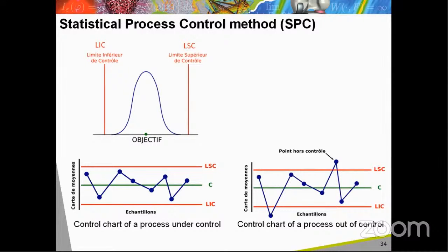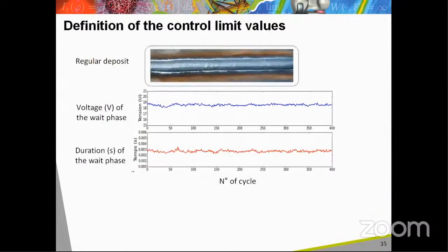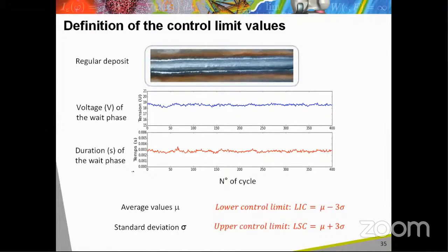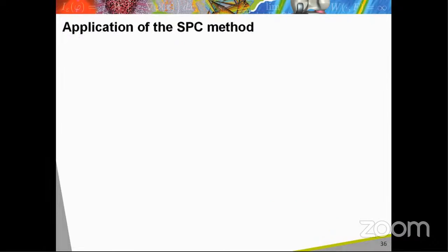One can see on this slide the evolution of the monitored parameters, the voltage and the duration of the wait phase of the CMT process for a regular deposit without geometrical flaws. The average values and the standard deviation of each parameter are computed, and the upper and lower control limits are defined. This slide shows an application of the SPC method to the monitoring of the deposit of steel beads.